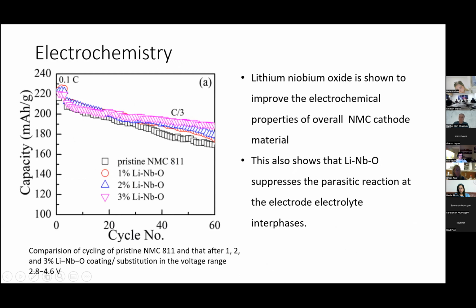When they conducted the electrochemistry of this, they saw improved electrochemical properties for 3% lithium niobium oxide coated NMC 811. As you see, the black rectangles here are the pristine, which is not coated. It retains 200 milliampere hour per gram capacity in the beginning, and later after 60 cycles, it has dropped to 180 milliampere hour per gram, a loss of 20. Whereas in the case of 3% lithium niobium oxide coating, it has decently stabilized the NMC 811.